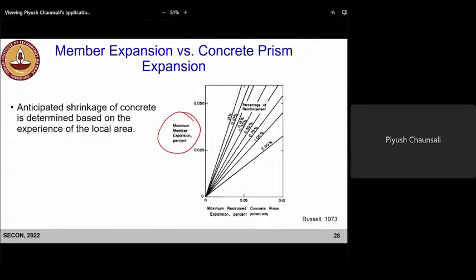So let's say we want to compensate this much level of shrinkage. And here you have charts where you have percentage reinforcement starting from 0% to 2%. So depending on the percentage reinforcement in the slab, let's say you are looking at a slab or bridge deck which has 0.3% reinforcement in this case. So what we see, we can then get,